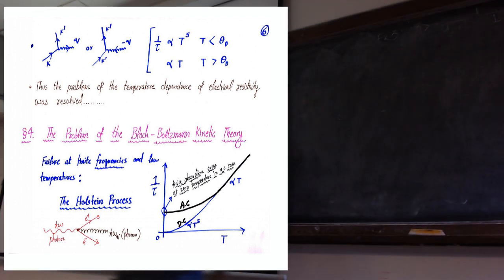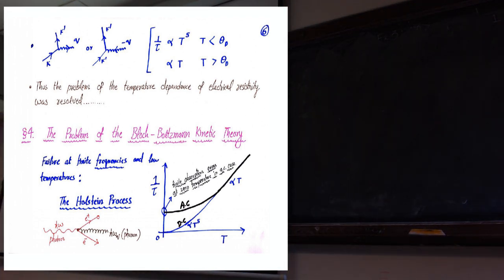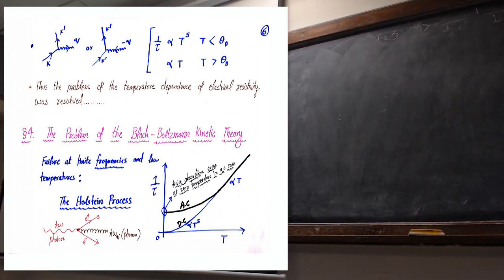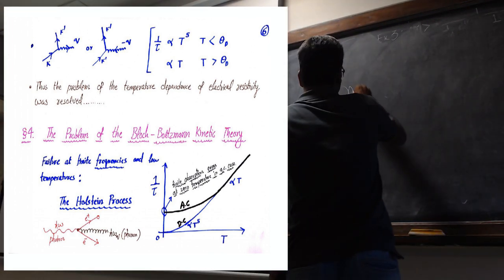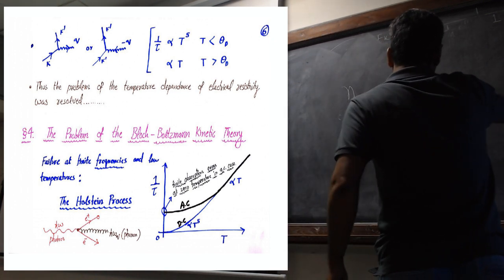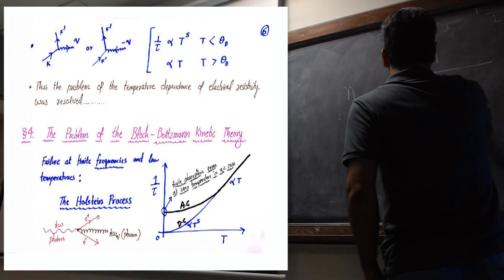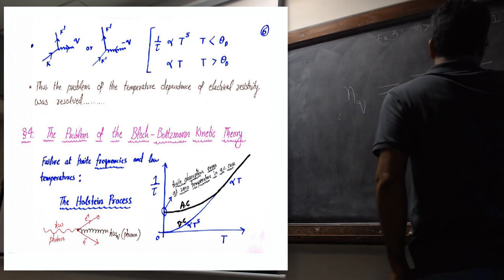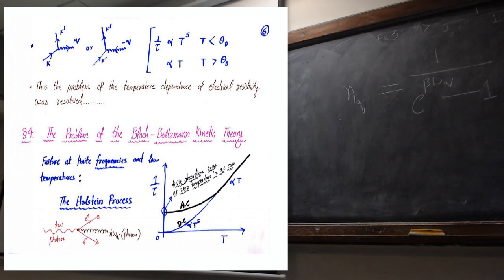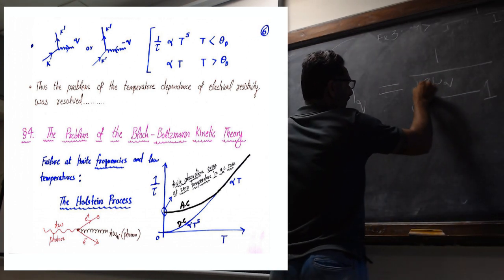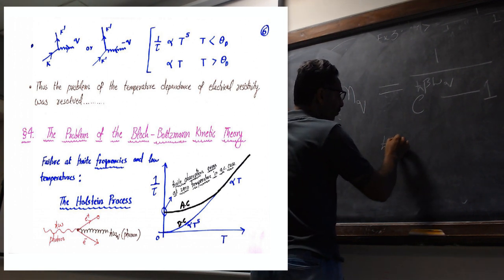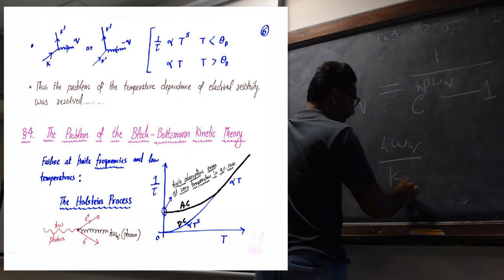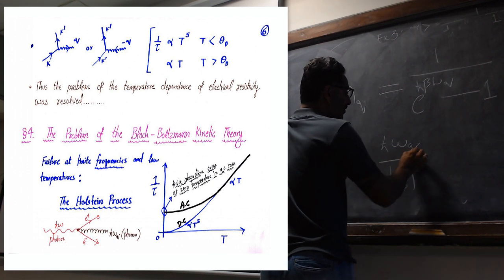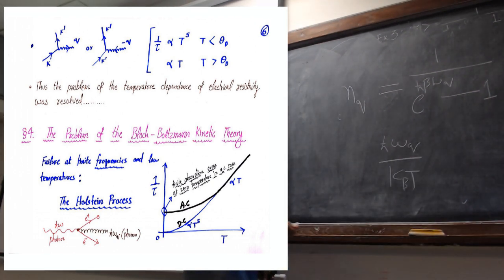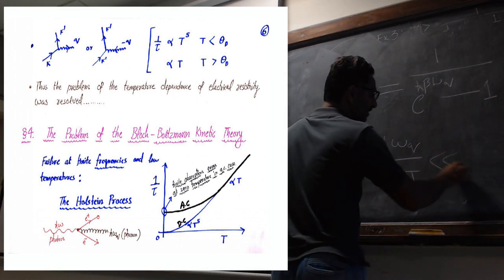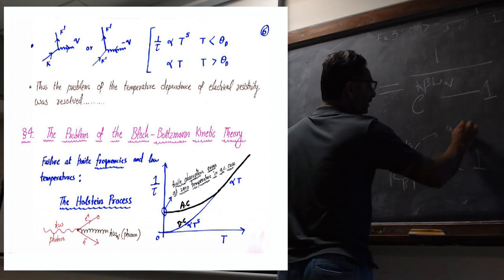So you see, what is the resistivity? It is the scattering, let's say. So how many phonons are there in one mode q? The number of phonons is given by 1 upon e raised to the power beta h bar omega q minus 1, the Planck distribution for phonons. Now at high temperature, this h bar omega q upon kBT, this phonon energy cannot be very large. It has a cutoff, called the Debye cutoff. So let us say that this is much less than 1, even when q is q_D.